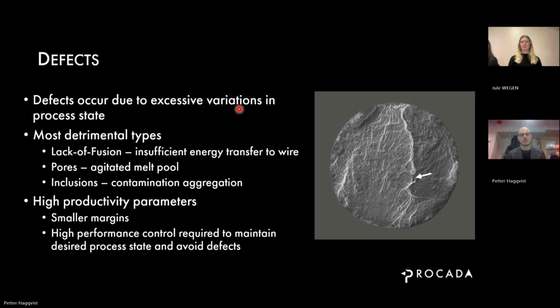And the most detrimental types are lack of fusion defects, where there's not enough energy instantaneously to transfer to the wire. That might be a global phenomenon, such as if we suddenly get a drastic reduction in the electrical preheating or the laser power, or it might be a local phenomenon where, for example, the underside of the wire is shaded and we don't get enough energy into a certain volume element. And if that volume element hits the unmolten substrate and it's not properly fused, then we get what's called a lack of fusion defect. These are usually only two-dimensional. They have very negligible thickness, but they are very detrimental to fatigue life.